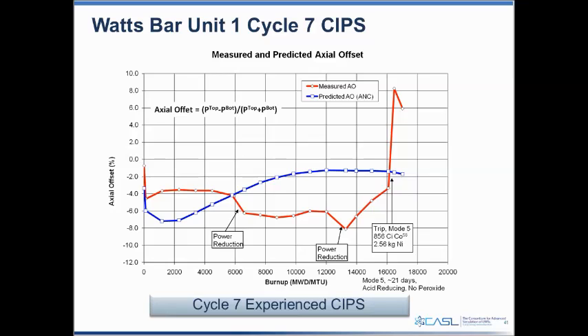But what you do see is after about 5 months of operation, or a cycle burnup of 6,000 megawatt days per metric ton, you do see this rapid drop in axial offset occurring. And that was a result of crud deposition and then boron deposition into crud.